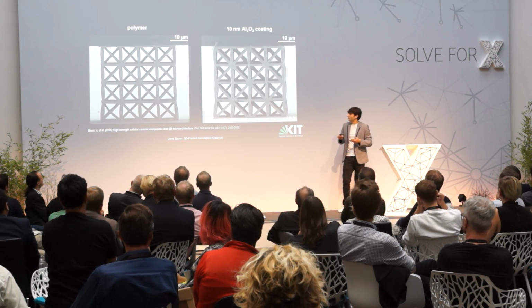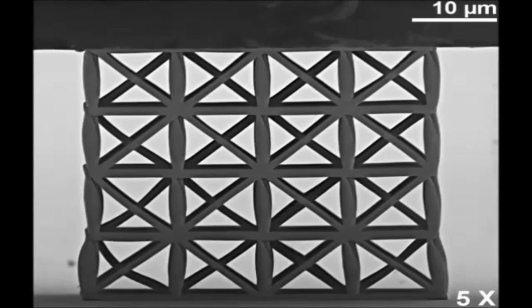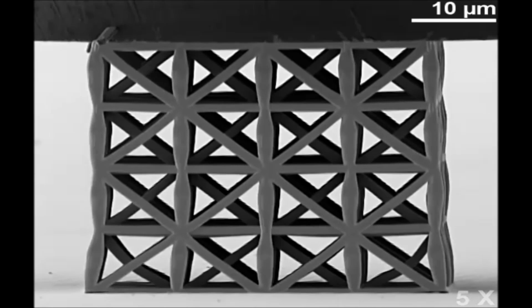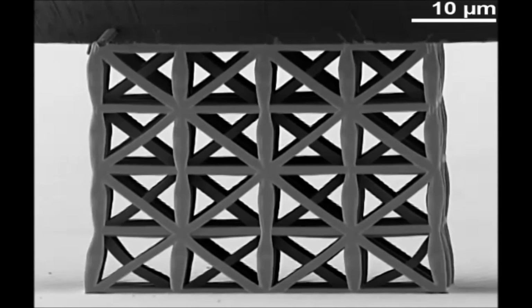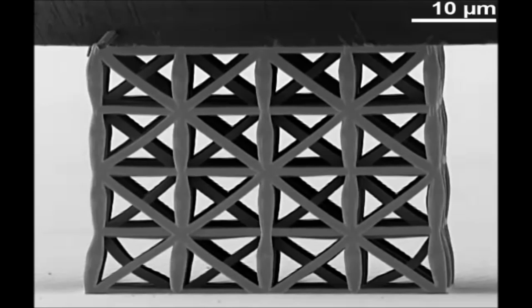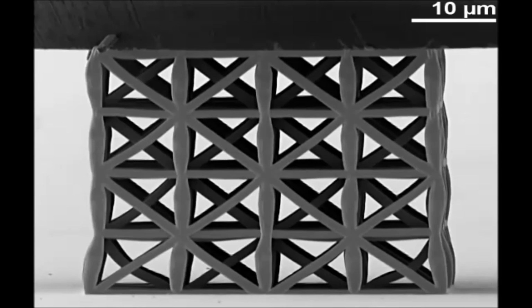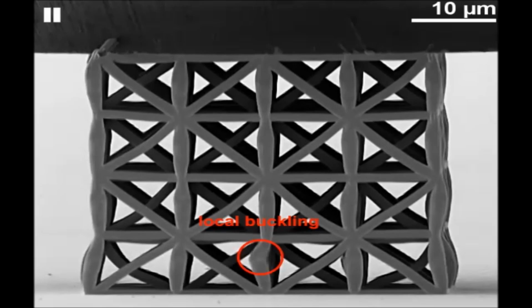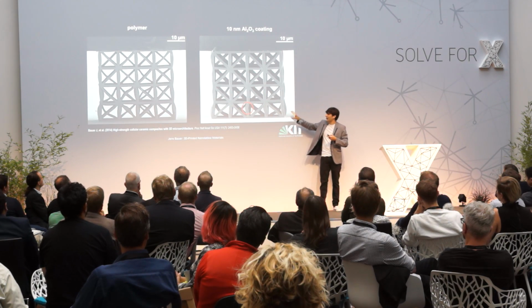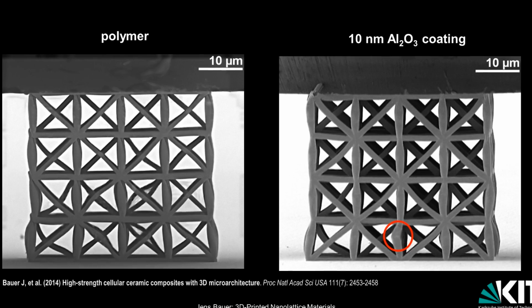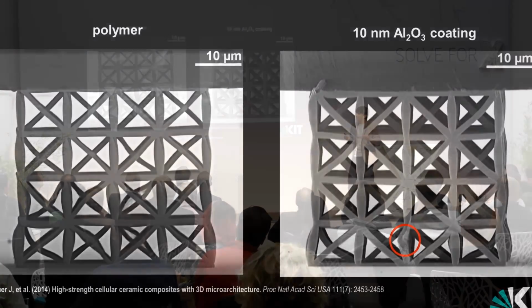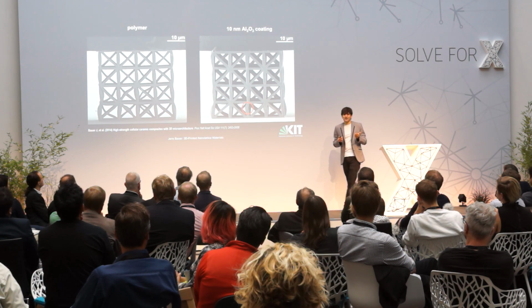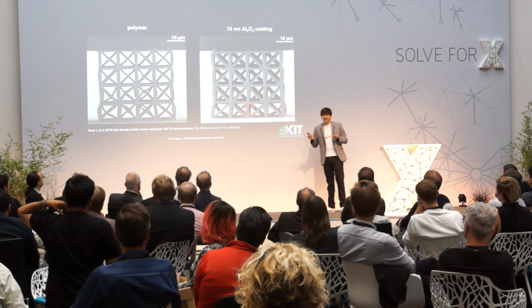Now, we tested those structures mechanically, as you can see here. So this is an experiment which has been carried out inside of a scanning electron microscope. And as you can see here, immediately, is that once a thin layer of aluminum oxide of just 10 nanometers is applied, the strength and the stiffness of that lattice increases dramatically. So here, we again got those still frames in the moment of fracture. So I think you already got it. It's all about size, as always in life, right? But in that case, it's the other way around.